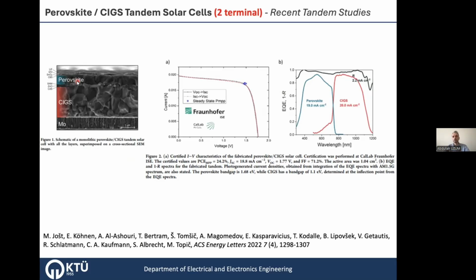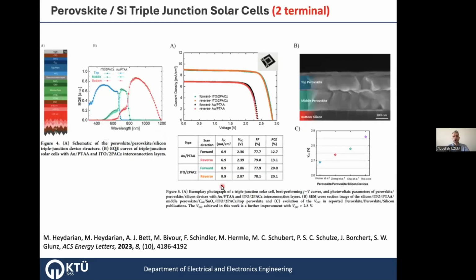Recently, you can see a lot of research on monolithic tandem solar cells. This one has an efficiency of 24.2%, and they provide the IV here. This is the certified IV by CalLab Fraunhofer ISE in Germany. So what is next? What kind of research is going on next? One example is the triple junction solar cell, with a silicon heterojunction bottom cell, a perovskite middle cell, and a perovskite top cell. You can have three different solar cells in the same standalone two-terminal device, but it still has lower efficiencies. Theoretically, they have very high potential, but they still provide only around 20% efficiency.